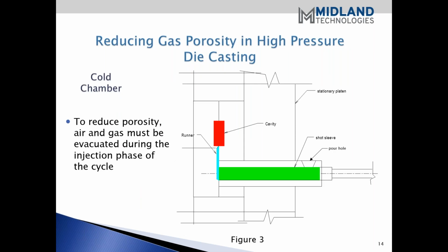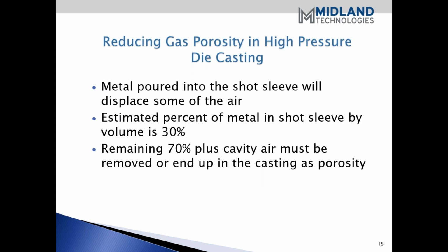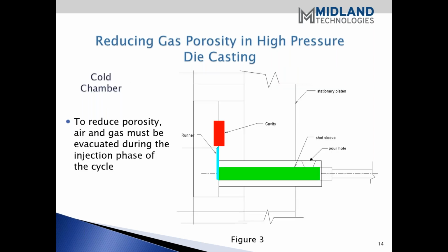Next slide. This is just a little schematic of a cross section of the shot sleeve, and of course to reduce porosity due to air, somehow we've got to get the air out of the metal feed system, and that evacuation begins when the plunger covers the pour hole in the case of vacuum. Okay, we'll move on. Just a note. Obviously, the green is the shot sleeve itself, runner, and then the cavity in red. Next slide.